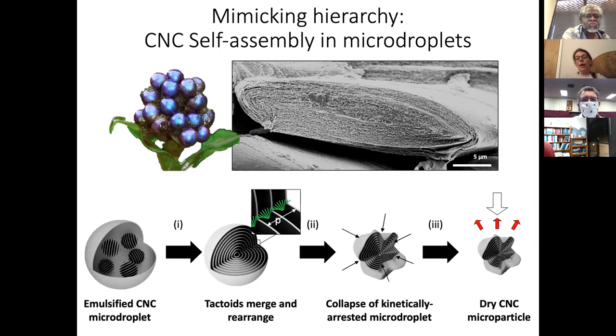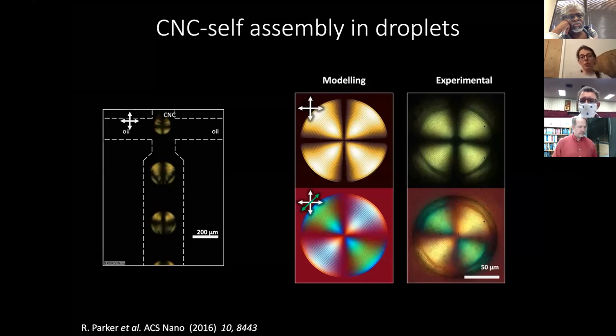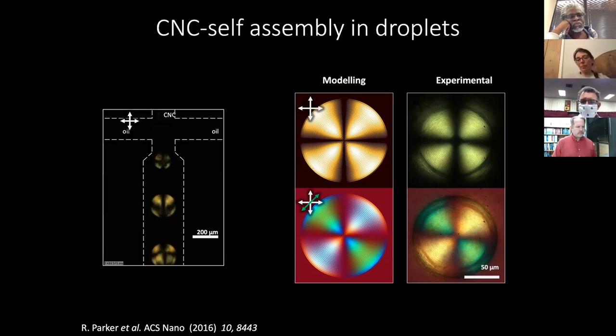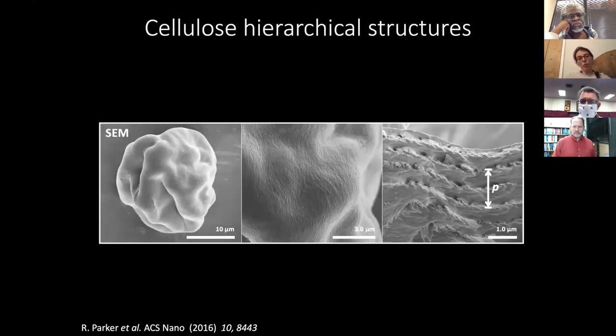So can we try to exploit this and make the self-assembly in the same way, try to confine it in a spherical geometry, similar to what happens in the cell wall? And yeah, we can partially do it, not fully, because as you can see here, if you try to make droplets, at a certain point you will always have a little bit of collapse and buckling, but nevertheless, it's possible. Especially when you use microfluidics, you can control and force this self-assembly, which can be properly modeled, and experimentally we see the same. And as I was telling you before, while you are evaporating the water, you can maintain this type of structure, but you always have a little bit of buckling.